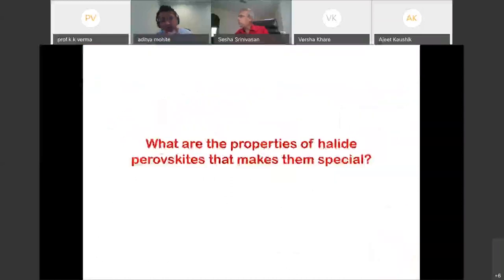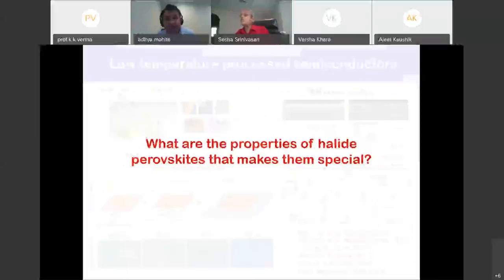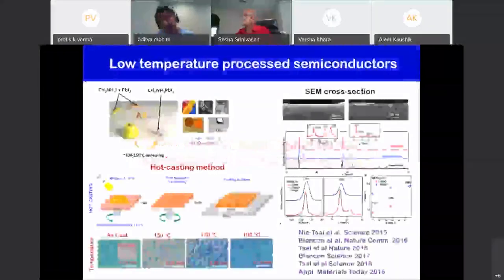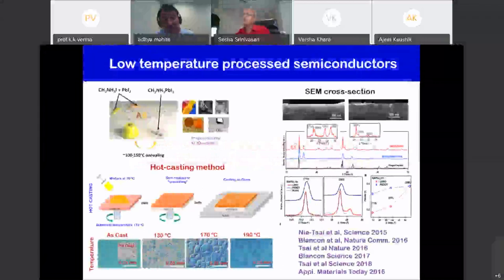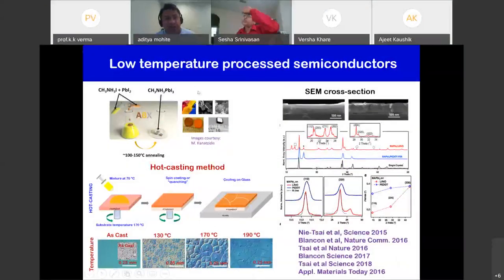So now let's look at what really makes these halide perovskites so special. The first thing is that these are low temperature processed, or in fact solution processed, semiconductors. You can do dirty chemistry. You can take any of these precursors, mix them in a solvent and get single crystals which are very, very large. You can see this is an image given to me by a close friend and collaborator, Professor Mercouri Kanatzidis at Northwestern. And you can see you can make really centimeter-scale single crystals.